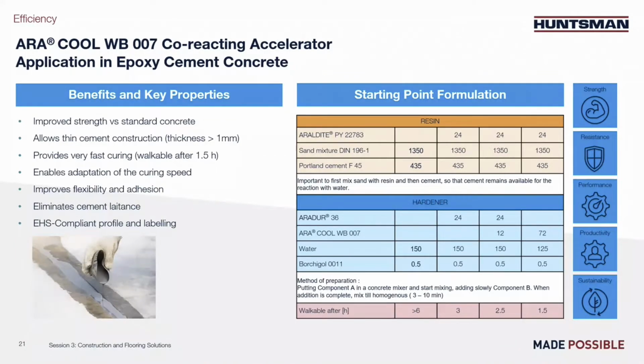On the left part of the table, our reference, cement: just water, sand, and cement. And to this, we add the epoxy Araldite PY22783 and the Aradur 36. Araldite PY22783 is a low viscosity emulsifiable epoxy resin. And what we can see in terms of effect is already with Aradur 36, you get a faster workability or settling of the material.